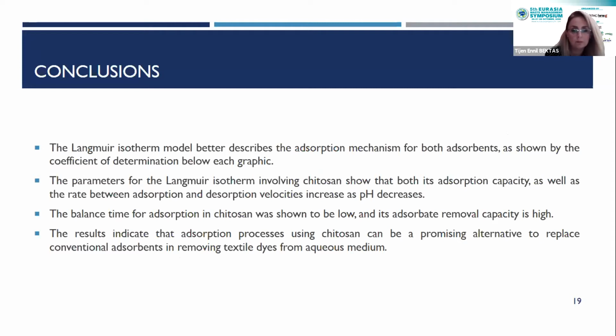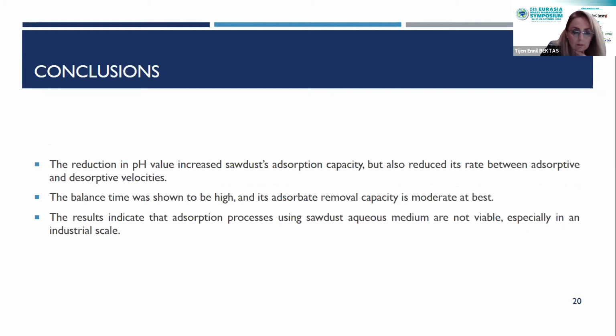The balance time for adsorption in Chitosan was shown to be low, and its adsorbate removal capacity is high. The results indicate that adsorption processes using Chitosan can be a promising alternative to replace conventional adsorbents in removing textile dyes from aqueous medium. The reduction in pH value increased sawdust adsorption capacity, but also reduced its rate between adsorptive and desorptive velocities. The balance time was shown to be high, and its adsorbate removal capacity is moderate at best. The results indicate that adsorption processes using sawdust in aqueous medium are not viable, especially on an industrial scale.